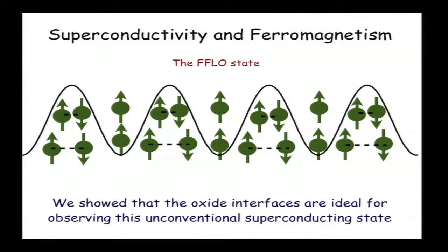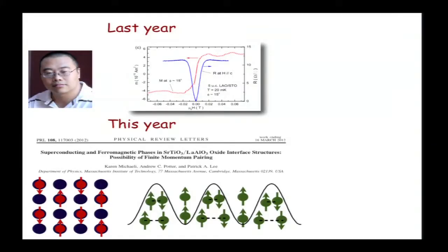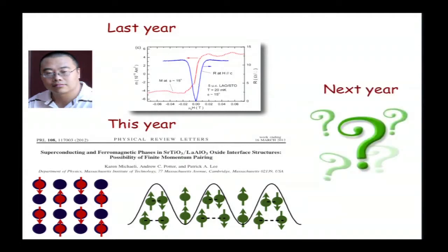One reason for that is that these FFLO states are usually very fragile. It's enough to have a small amount of impurity, and it will immediately disappear. What we have shown is that in these oxide interfaces, there is an opportunity to see a very stable FFLO state that is not going to be destroyed even if we have a large amount of impurities coming from the surroundings. So to conclude, last year, we had Lu Li showing us the magnetism and superconductivity and their coexistence in these materials. This year, I was explaining the origin of the ferromagnetism and how we can explain the coexistence of ferromagnetism and superconductivity. And I'm looking forward to seeing what we will hear next year.